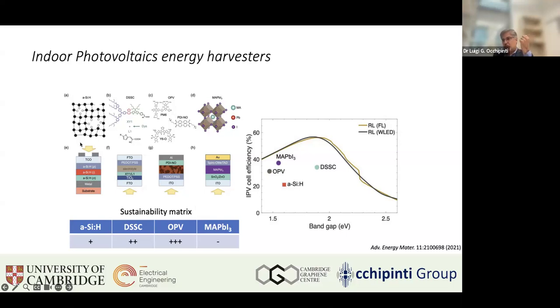Actually, combining with the sustainability, for instance, starting with the hydrogenated amorphous silicon architecture, this is probably the main commercially available technology for indoor photovoltaic, with good sustainability in terms of economic impact, because it relies on well-established manufacturing processes. However, the technology is limited by a relatively low conversion efficiency in the indoor range, and also there is an intrinsic degradation mechanism which is induced by light exposure in the first few months of operation. So these are the main limitations for which sustainability is still in the plus, but of course it's not great and it could be better when considering other technologies.